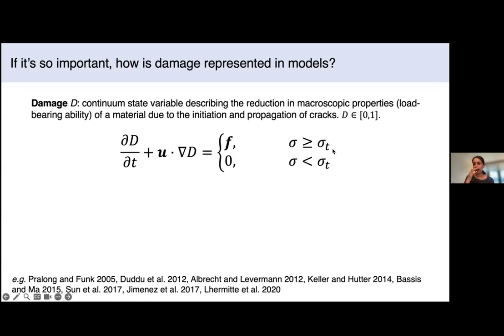So the sigma T parameter is the strength of the ice. It's designated T because we typically think of the governing fracture process as being fracture in tension. So this is the tensile strength of ice. In this case, damage only accumulates if stresses have exceeded this threshold of the tensile strength of ice. If they do not exceed that, then there's no additional accumulation of damage.